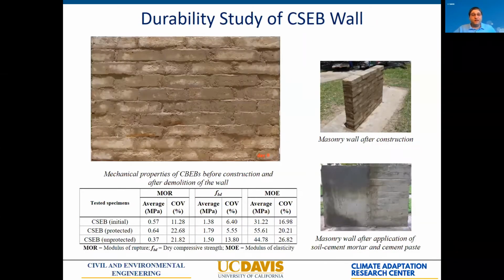Louisiana. So what we did was we built a small masonry wall and we tested this wall by just leaving it for 6 months outside in Baton Rouge. Actually, during that period, we had 2 strong tropical storms that passed through the town. So it was actually a pretty severe test for the wall. And in this wall, we protected one side of the wall with a soil cement mortar, a kind of stucco made with the same mix used for the bricks, in order to see how the wall was performing.